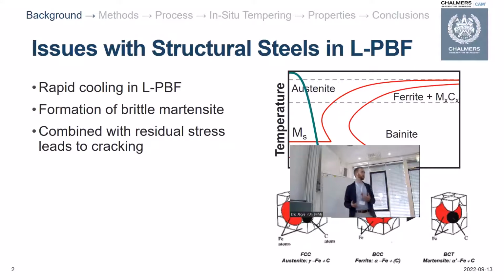And as you probably all know, it's a problem in LPBF materials because there's also noticeable residual stress in your material that comes about due to the rapid solidification conditions that you have, in addition to the volume expansion of your martensitic phase. And so the hope when you want to develop this alloy is to find how we can mitigate this cracking issue, either by changing your alloy composition or your processing parameters. And that's what I'll be covering today.